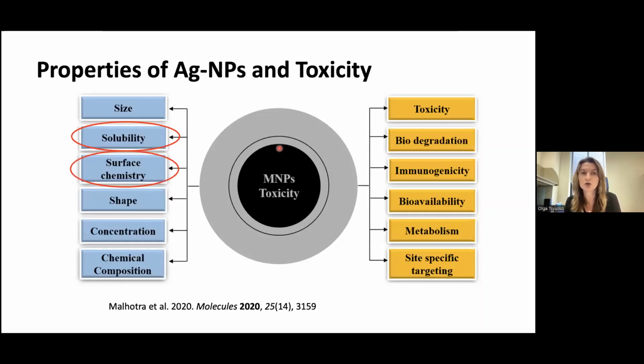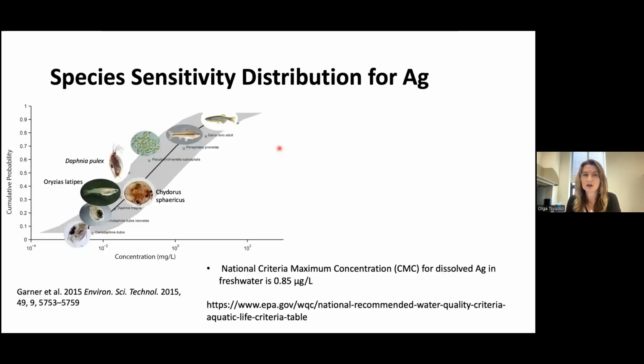Another thing is that during environmental transformation, there is a change in their surface modifications. Again, it changes their properties and hence toxicities. So this is a species sensitivity distribution specifically for bare, non-coated silver nanoparticles. It's a statistical approach tool, and it's based on 10 separate studies for LC50, so 50% mortality. And the distribution is fitted with a 95% confidence interval for all those 10 species.